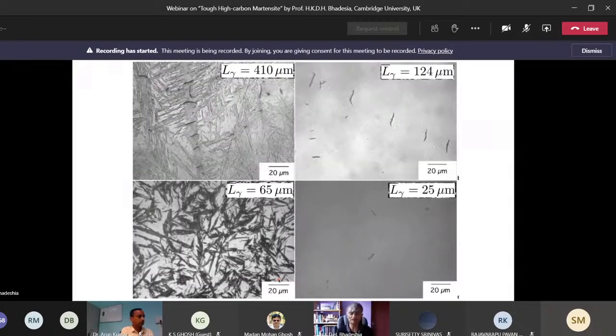Now here is a set of experiments which were done by Chatterjee, who is now at Tata Steel. And here we are altering the grain size, 410 micrometers, 124, 65, and 25. And you can see these cracks in the martensite plates. This is the unetched sample, just to show you the cracks more visibly. And as we go down to a 25 micrometer grain size, the number of cracks decreases.